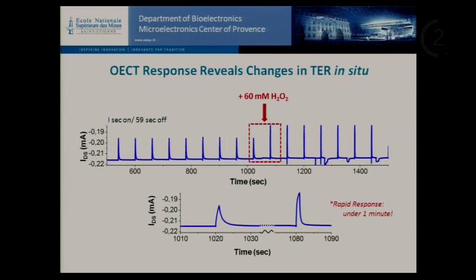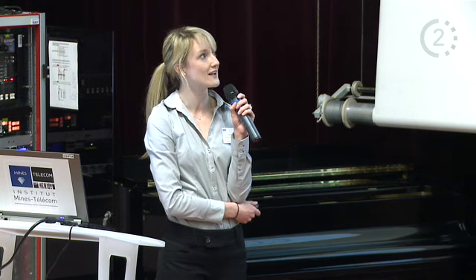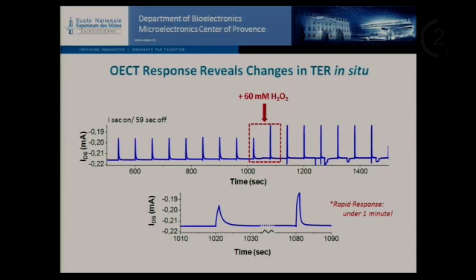The great thing about our device is we can watch this effect in situ. We apply periodic square pulses to the gate electrode. In this case, 1 second on, and then we wait a full minute. So each one of these pulses is a minute. We add 60 millimolar of hydrogen peroxide, and we immediately see a change. This is a fast effect and a fast measurement system.